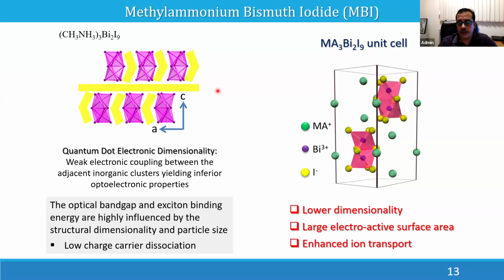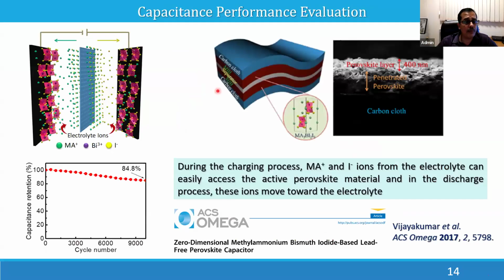So we try to use it for the capacitor application. There, ion migration can play a key role. So we developed a capacitor device like this, and we incorporated the material in a carbon sponge kind of electrode, and we impregnated it with our perovskite material, and tried to understand how the ion migration is affecting. We were able to get a very beautiful capacitance which is pretty stable for several cycles. And this was the first lead-free perovskite based capacitor device application, and we published it in 2017.